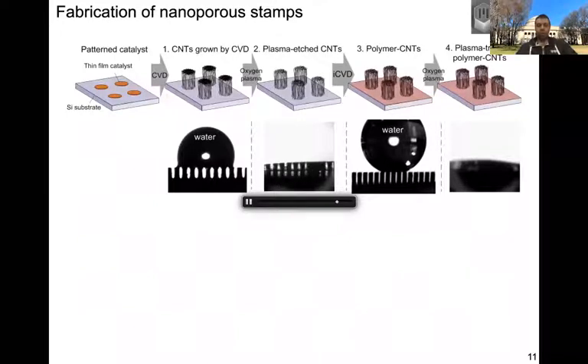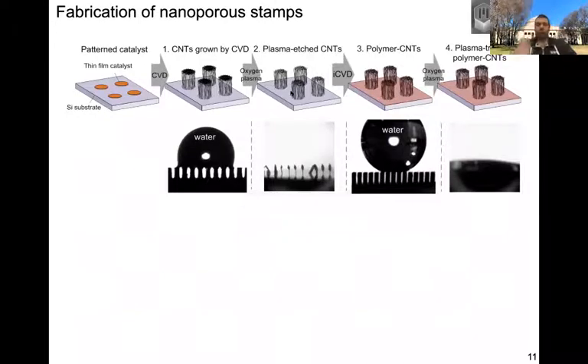First, what happens if we take a drop of water and we evaporate it on non-reinforced CNT microstructures? They densify via capillarity when the ink infiltrates and then recedes. So beautiful process, but a bad one for what we want to do here. But after actually 2 consecutive surface treatments, after growing the CNTs, we plasma etch them to open up the top surface, and then we coat them conformally with a polymer. We can have stable nanoporous CNT structures. The video hopefully playing now shows liquid receding and the pillars remaining the same geometry.